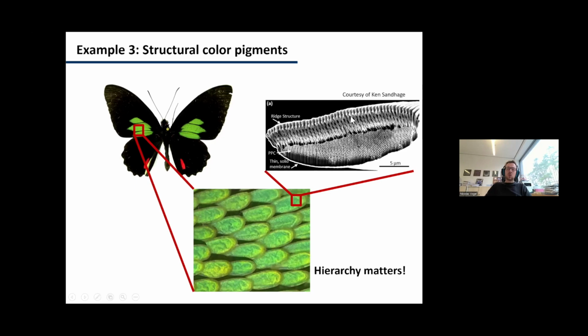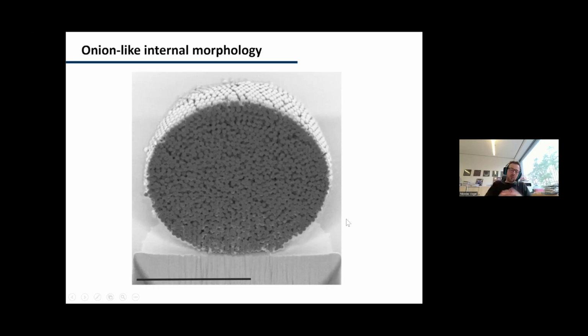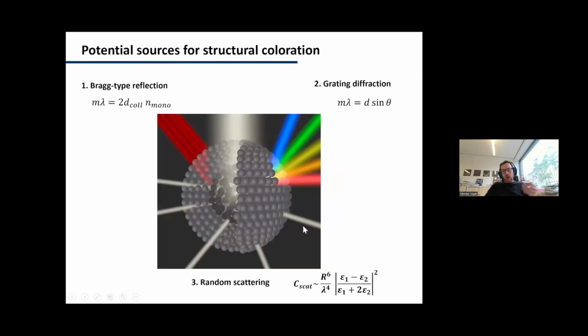So in this case, also the hierarchy is important, in particular this nanostructure. And when we cut open one of our superparticles, if we make this from primary particles, we see that we, in a sense, have a very similar structure to the butterfly wing, because we have very ordered layers here, and we can make them in the same size range as the butterfly. And that will lead to structural coloration by the same interference effect that we observe in the butterfly. And in a sense, if we sum this up a little bit, there are multiple optical effects in such superparticles that can take part at the same time.